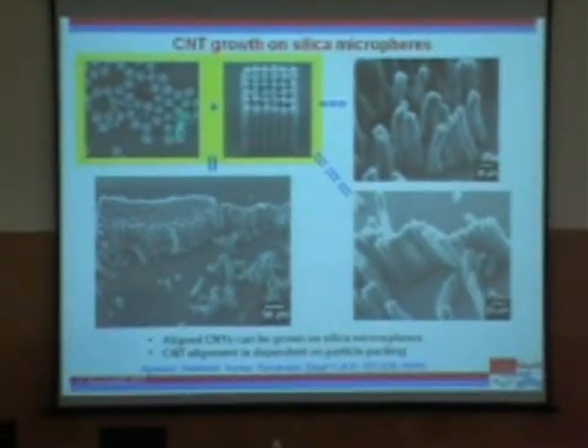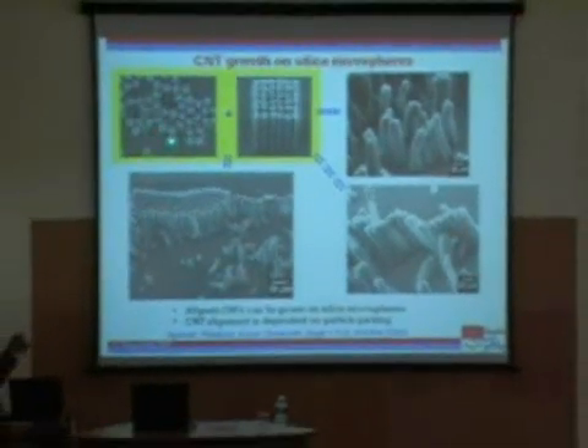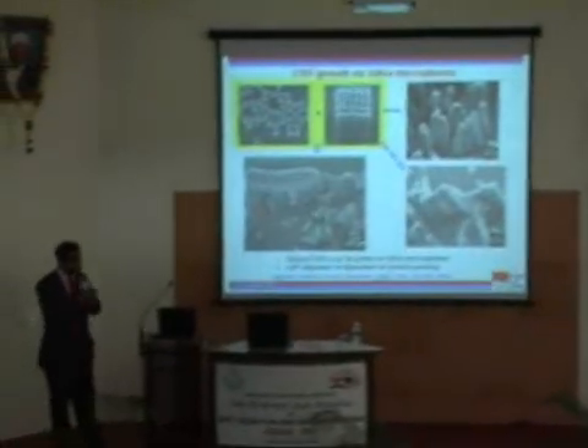So what we did was we took a bunch of silica particles of different sizes to see if there is a substrate size dependence in terms of getting the carbon nanotube growth, and we find that indeed there is. Here you can see that the carbon nanotube bundles actually grow on the particles of silica, and also, in fact, inherit the shape of the assembly of the silica particles. You can get walls of the carbon nanotubes, or you can get also 2-dimensional assemblies like this without any problem.